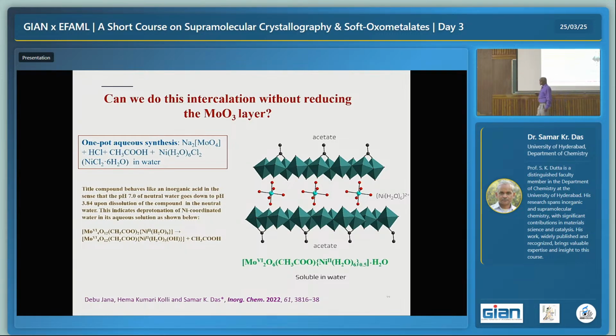So, just mix them together. Within 6 hours, you can get nice brown-colored crystals. And when we solved the structure of that crystal, we found MoO3 in between nickel aqua complex, and it is not molybdenum bronze, by the way, because they are not reduced. I didn't put in any reducing agent, and because it is a plus charge, something has to be there to counterbalance the charge. So acetate gets coordinated.